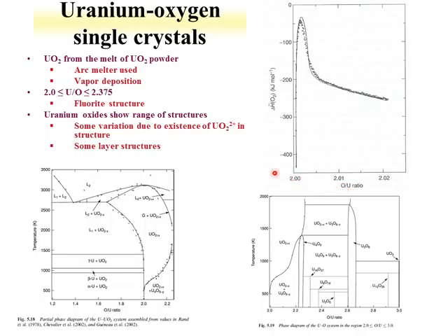And one of the ways of measuring that ratio is by looking at thermodynamic data like this, the Gibbs free energy as a function of the oxygen to uranium ratio. If one takes material and evaluates the enthalpy, not the Gibbs free energy, the enthalpy of the system, one can determine the oxygen to uranium ratio from this.